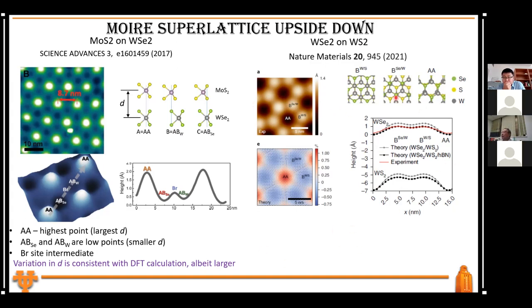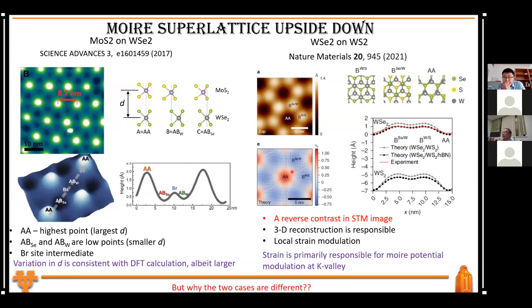But then they say there is some kind of relaxation, even for this large lattice mismatch system. In that calculation, there is some kind of 3D reconstruction in the third dimension. So as a result, even at the AA site, you have a large interlayer spacing, but the strain pushes this one such that when WSe2 is on top, the AA site becomes dark and the AB site becomes bright. So this is their interpretation. As a result, there is a large in-plane strain.